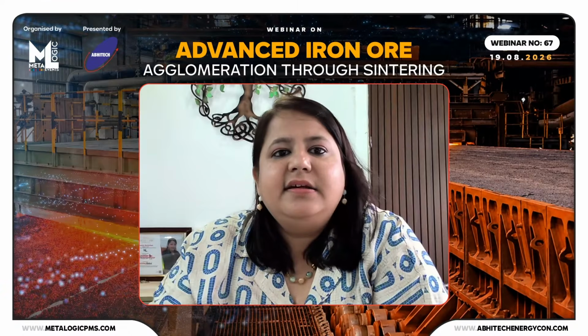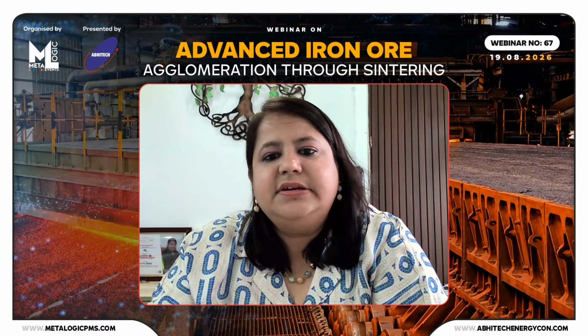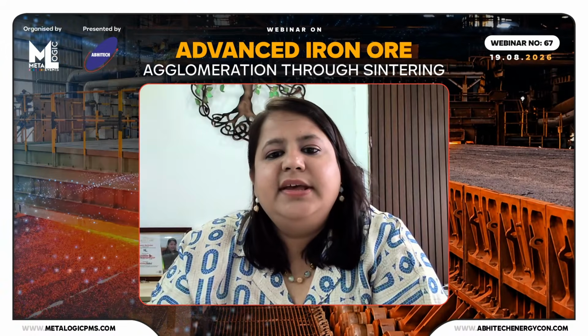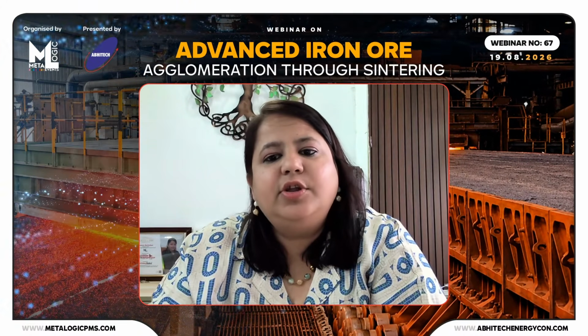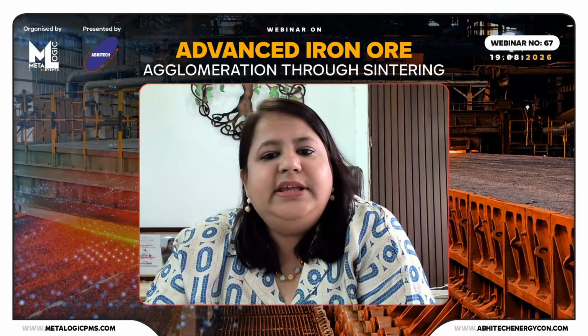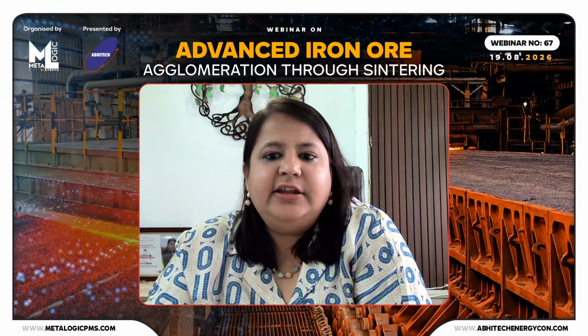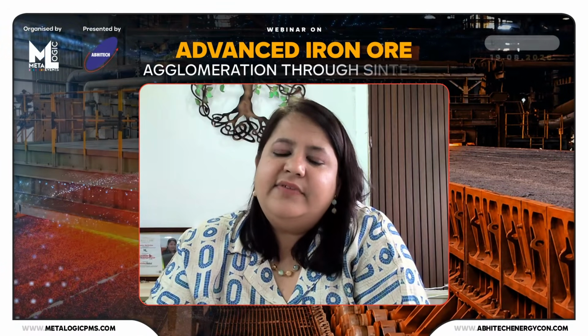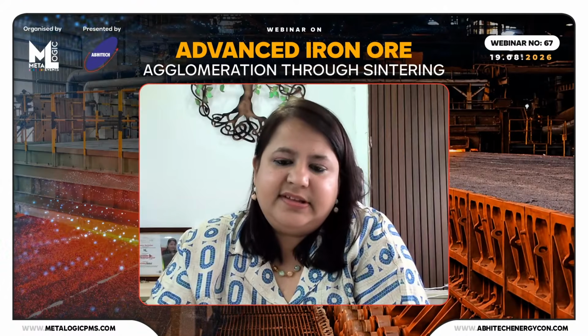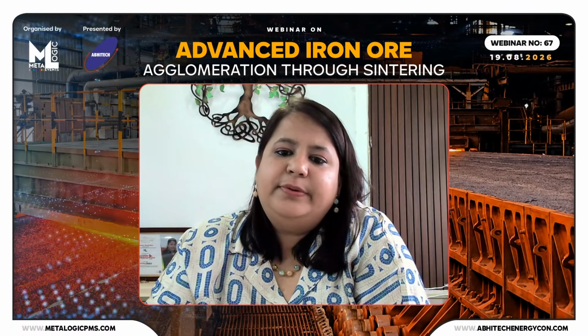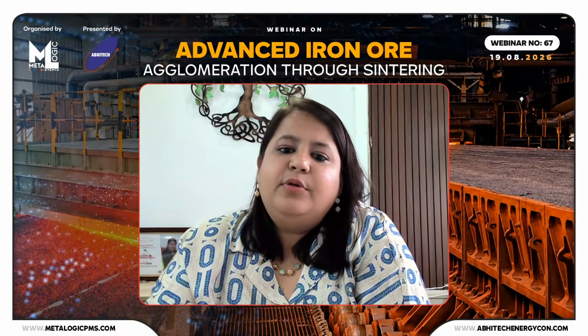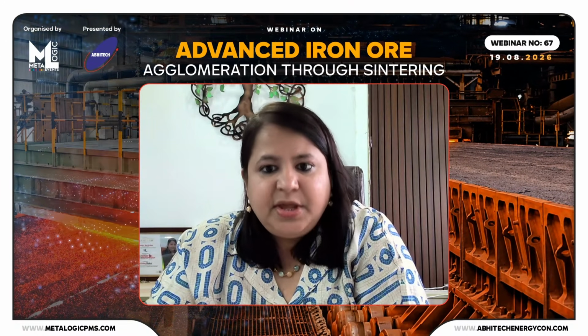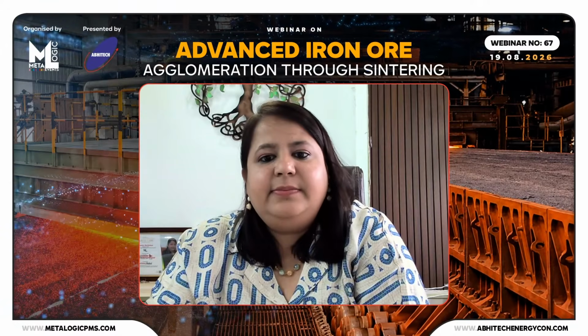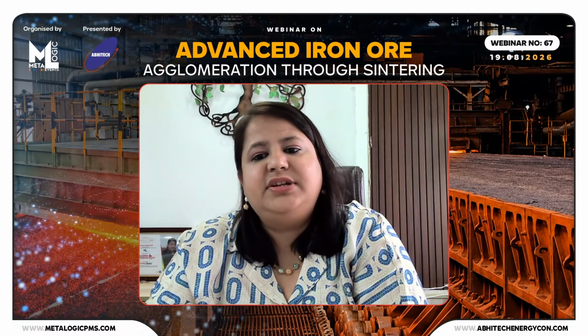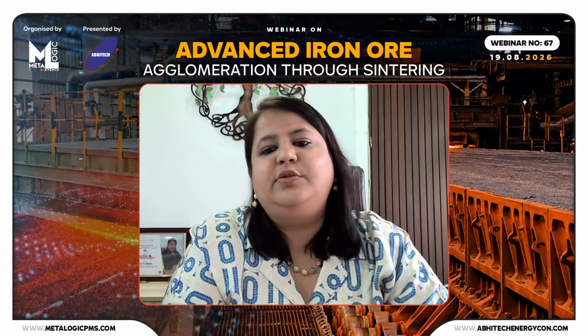Okay. There is a general question from Mr. Glenn from Goa. He's asking, when we talk about low-grade iron ores, what would be the preferred iron ore content, silica and alumina content for input for sintering plants? Can a typical ore having an Fe content of 50 to 53%, alumina 4%, silica 4 to 6%, moisture content about 10% be suitable? Or is beneficiation needed prior to improve the input feed to sinter plants?